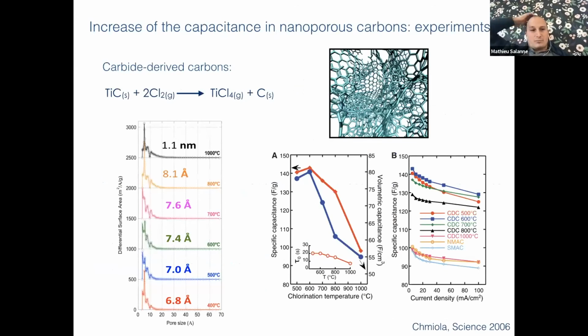So the second point is that we also, on top of using concentrated electrolytes, we have nanoporous systems. And so the main experimental results obtained in 2006 by the groups of Gogotsi and Simon were by using carbons in which they were able to tune the porosity by playing on this reaction here, starting from titanium carbide and chlorinating. You end up with titanium tetrachloride, which is evaporating, and you end up with a nanoporous carbon. And depending on the temperature at which the synthesis occurs, between 1000 degrees and 400 degrees Celsius, you have a porosity that is centered around 1 nanometer, or even you can go down to 7 angstrom.